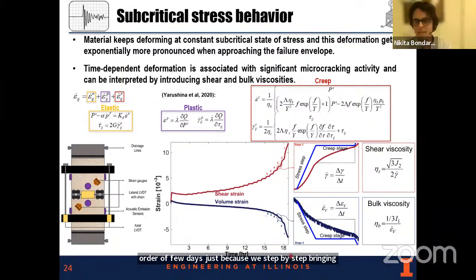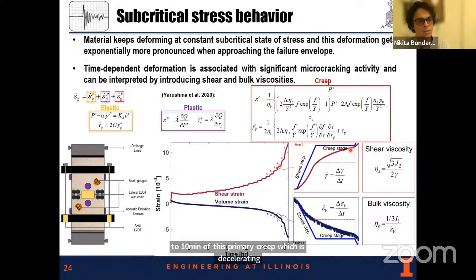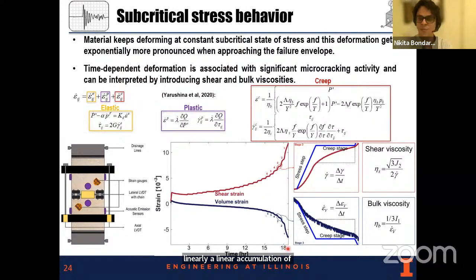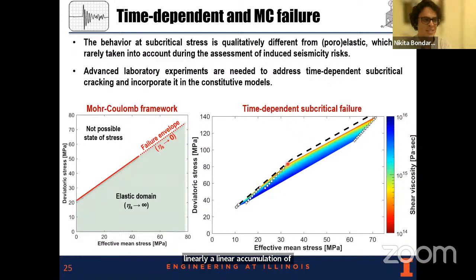So here is a real example of one of the tests, and this is not an illustration. This part is associated with the change of the stress, and after that we have probably 5 to 10 minutes of this primary creep, which is decelerating, and after that it's more or less steady state. We have longer stages where we can see linear accumulation of strain. But the reason we finish within 1 day is just because we are getting closer and closer to the failure envelope, and you can see the final moment where we start to have tertiary.